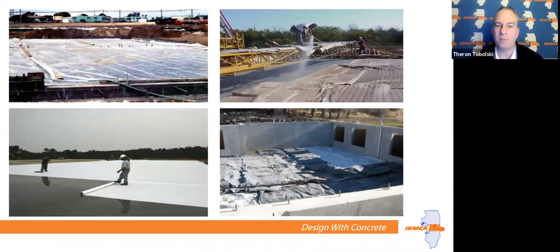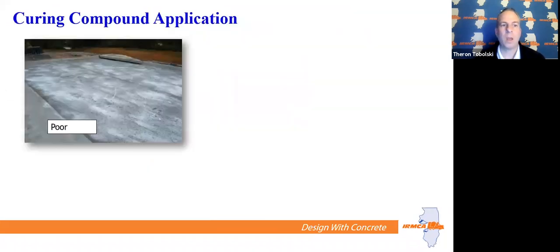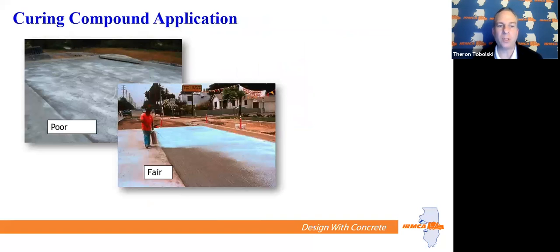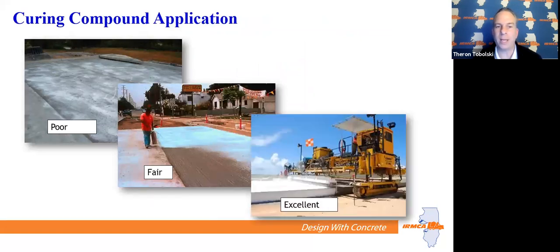You can see some of the different types of curing applications here. And in the bottom corner, you actually see the winter blankets down on the concrete pavement to make sure we got that temperature part of the curing covered. Here's an example of curing that's poor. They sprayed the white pigment on it, but you can see all the gray through it. It's really a bad job of curing. Here we see a much better job. They're putting it on a little thicker, really covering that concrete. And this is actually how your concrete should look when you cure it. A white pigment is good to specify because you can actually see the rate at which they're applying it. And that's the goal, is to lock that moisture in there. So you really need good coverage.